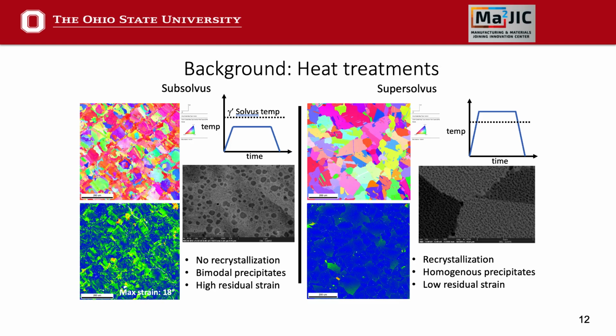Yeah, so these alloys in the wrought condition are all post-processed, so it's something we do need to do with the additive manufacturing alloys as well. The wrought alloy is completed in the subsolvus condition, and the reason for this is they experience pretty rapid grain growth in the supersolvus condition. For the additive manufacturing alloy, we evaluated both this subsolvus condition, which is the traditional Rene 65 heat treatment, as well as evaluating the alloy in the supersolvus condition.